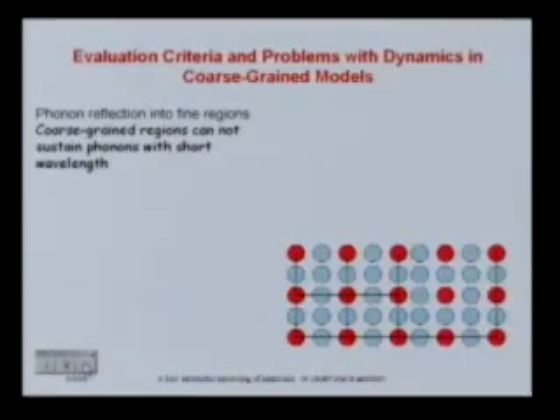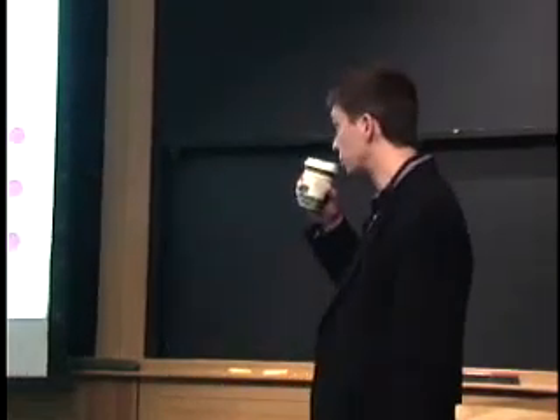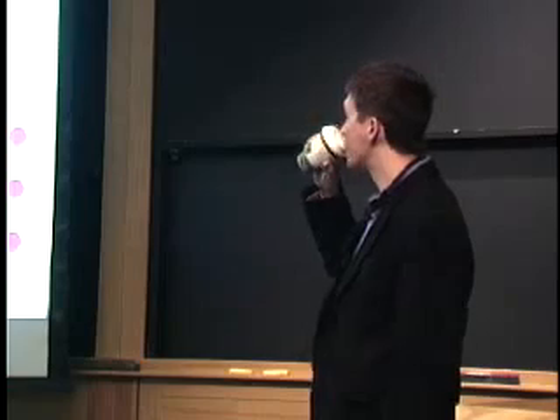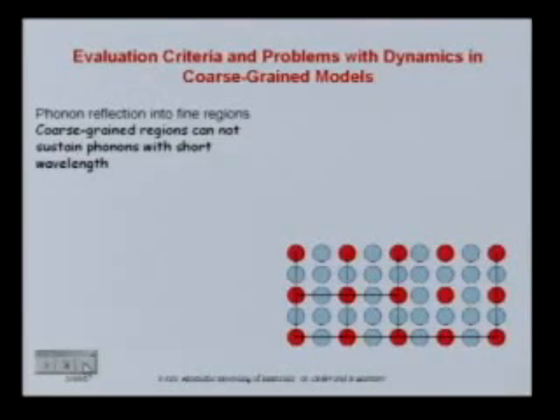There are essentially 2 major problems with almost any coarse-graining scheme, and the first one is the worst. Whenever you go from, let's say, atomistic out here to coarse-grained level 4, coarse-grained another factor of 4, you cannot sustain short wavelength phonons in the coarse regions.